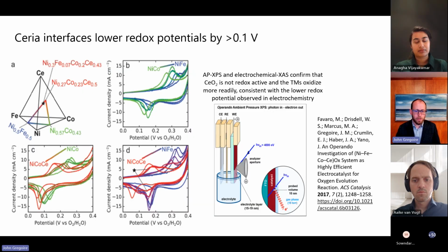To do that, we turned to looking at the initial oxidation of these materials in electrolyte with a series of in situ and operando XPS and XAS studies, which really corroborated what we started seeing in these high sweep rate cyclic voltammograms. I'm going to focus on this composition line that's similar to the one I showed you before, where if you start from transition metal oxides, you see a redox wave corresponding to, for example, nickel 2 to nickel 3 oxidation at these potentials, well correlated with the onset of OER activity. But as you add the ceria, you can march down that redox potential by a sizable fraction of a volt.